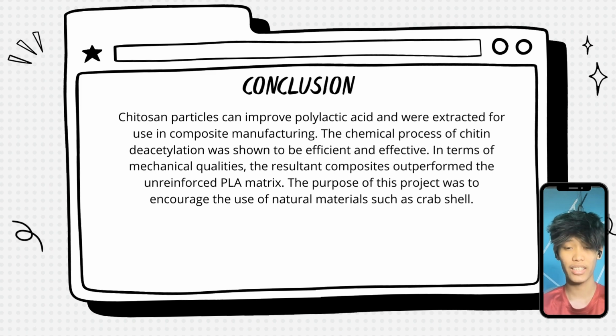And last but not least is our conclusion. In our conclusion, we can conclude that Chitosan particles can improve polylactic acid and were extracted for use in composite manufacturing. The chemical process of chitin deacetylation was shown to be efficient and effective. In terms of mechanical qualities, the resultant composites outperform the unreinforced PLA matrix or polylactic acid matrix.